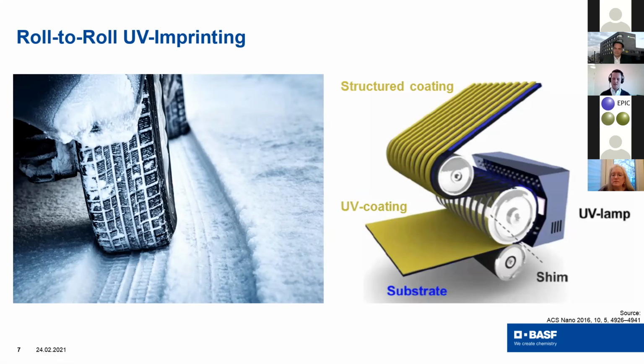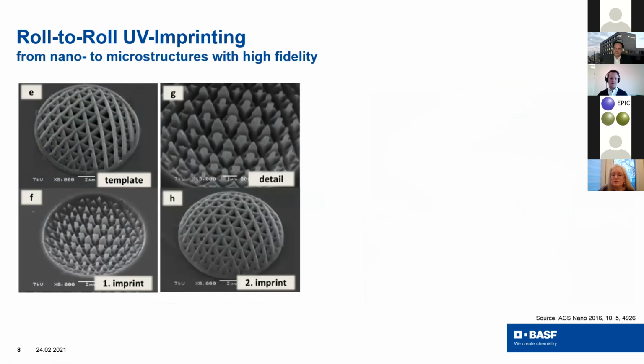However, this technology offers quite a lot of interesting capabilities. Most of the work done in literature is done on nanostructures. Morpho was such an example. Here on the left, you see an artificial diatom structure. This was a template. The people copied it in UV coating one time. You see here the scale of 2 microns, so really high fidelity in the nano range. And then here they did a second copy. So you can see it's a very good way to copy things on a nanoscale.